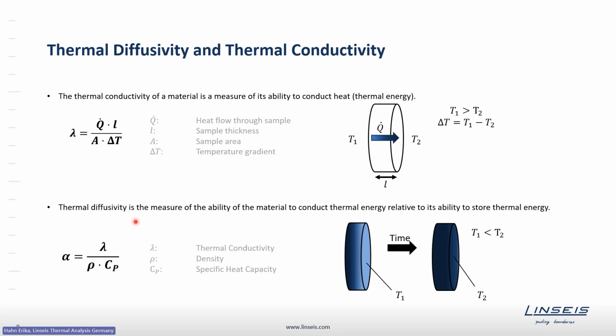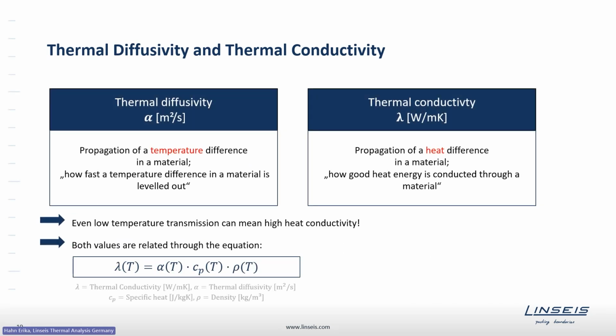The thermal diffusivity, in contrast, is the measure of the ability of the material to conduct thermal energy relative to its ability to store thermal energy. So here we already see that the thermal diffusivity is linked to the thermal conductivity, and more or less you observe how fast a temperature difference is propagating within a material. So this is summarized here as well. The thermal diffusivity with the unit meter squared per second is the propagation of a temperature difference in the material, and the thermal conductivity with the unit watt per meter Kelvin is the propagation of a heat difference in a material.